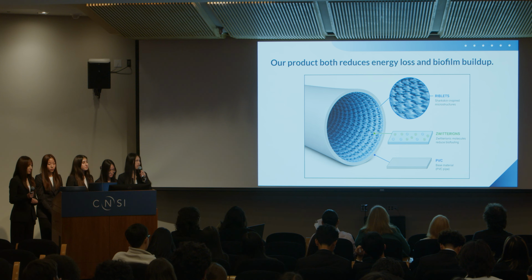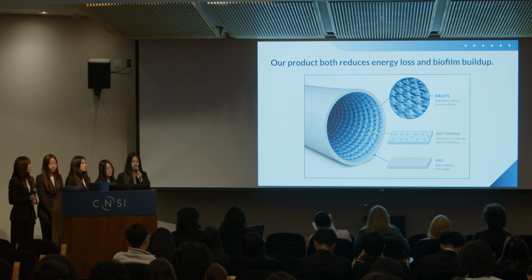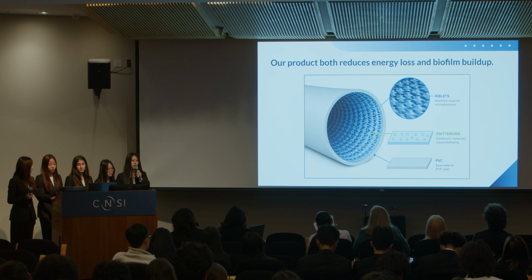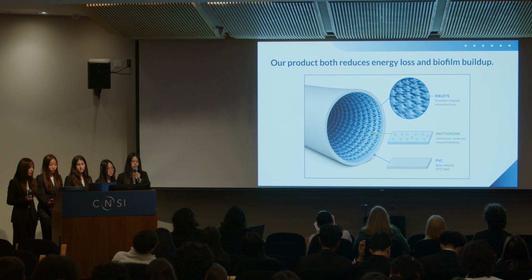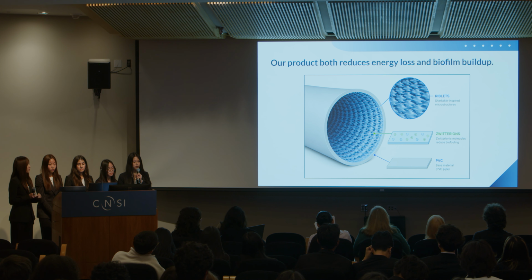SharkPipe is a modified PVC water pipe designed to reduce energy loss and prevent biofilm buildup by engineering the inner surface of the pipe at the micro and nano scale. Instead of leaving the interior smooth like traditional systems, SharkPipe uses a combination of shark skin-inspired riblet microstructures, as you see here, with integrated Zwitterionic polymer technology to improve flow and keep the pipe clean over time.